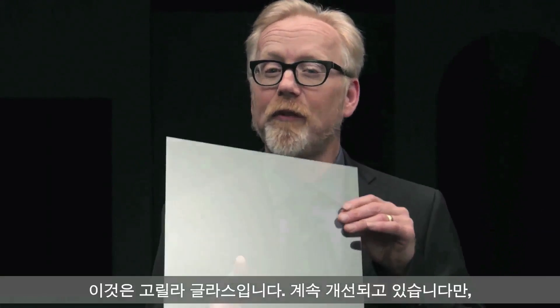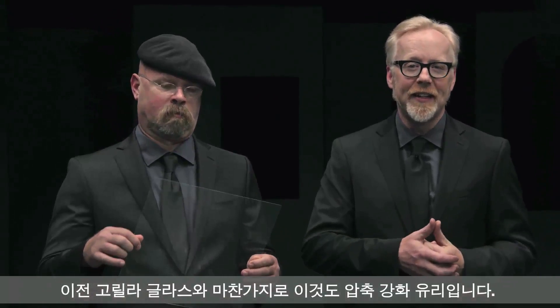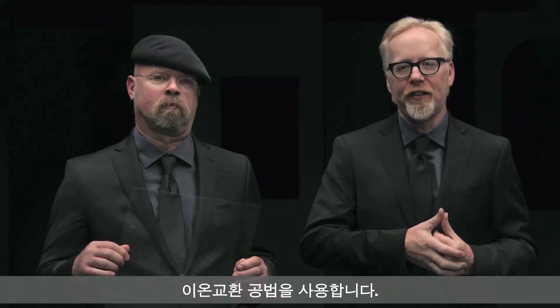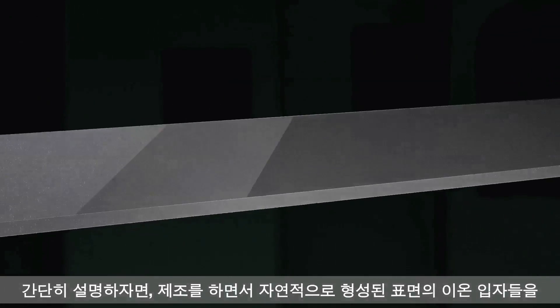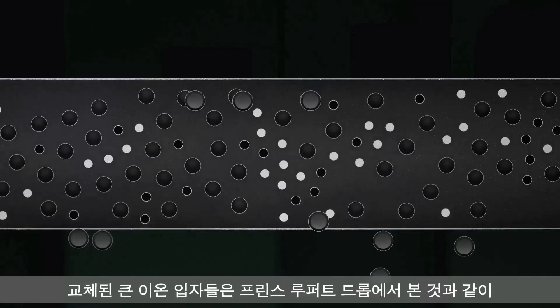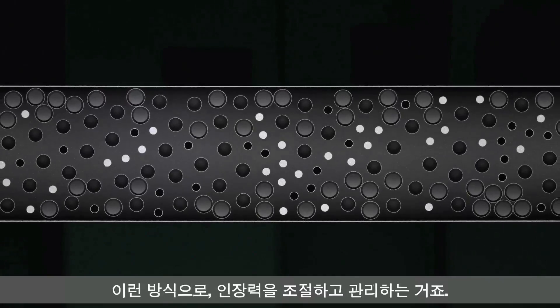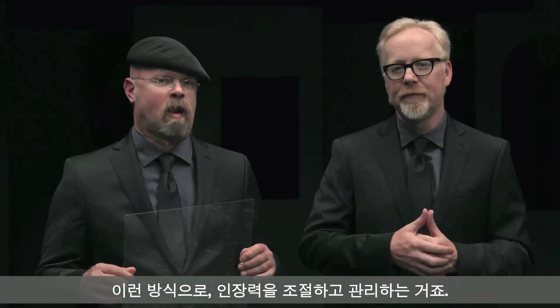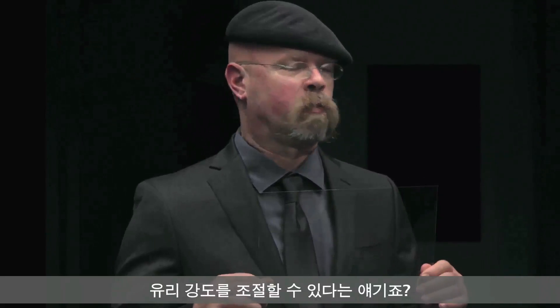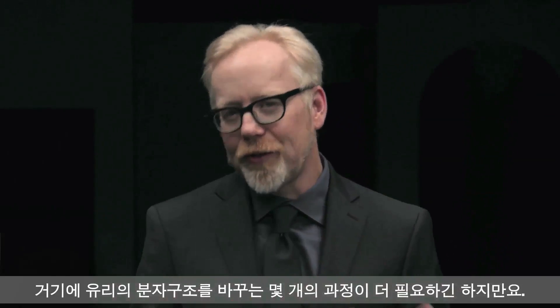This is Gorilla Glass. It has been refined over time, but like all Gorilla Glass variants that came before it, it is compressive strength glass. But it's not made in the same way as we just demonstrated — the rapid cooling method. Instead, Corning uses an ion exchange process. To break it down simply, the surface ion particles that naturally form during manufacture are replaced with larger ion particles. Once exchanged, the larger ion particles create the same sort of inward pressure that we see on the Prince Rupert drop, and with this method they are able to control and manage the resulting tension.